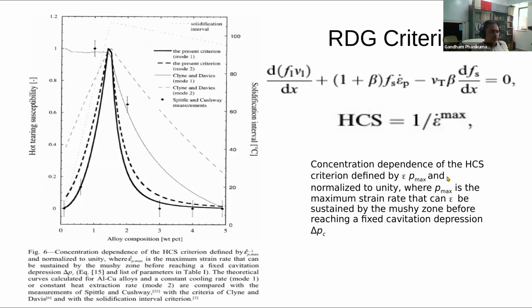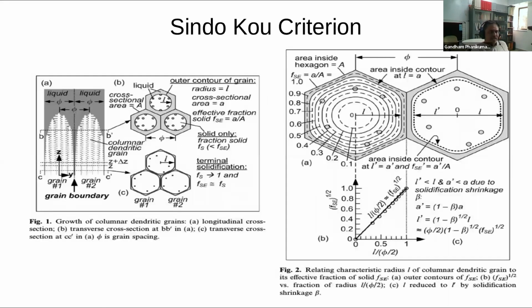The criterion shows you that the alloy composition where the freezing range is high also has high susceptibility. So when you choose an alloy for printing, make sure that the alloy has a small freezing range if you have a choice, or at least a eutectic formation towards the end of solidification. That way, at least you can avoid the crack formation. Microstructural assumptions are made in Kou's criterion, which lead to its limited applicability.